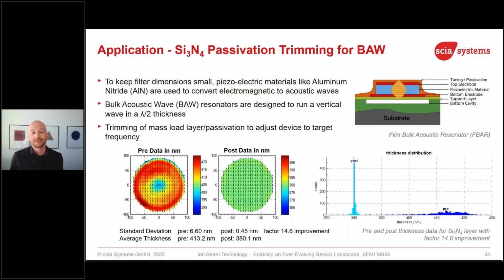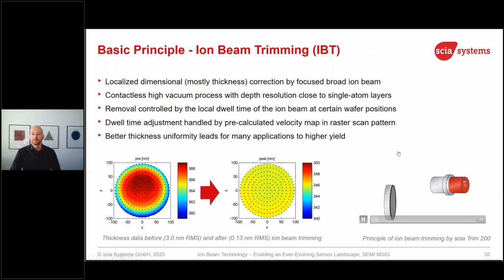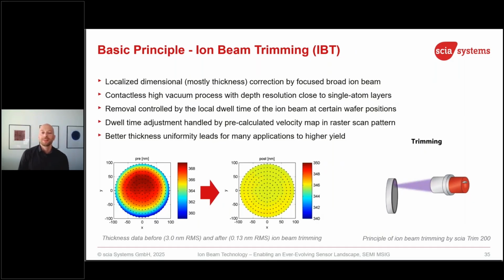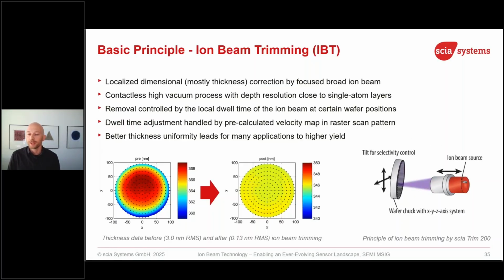Otherwise, your yield is very bad. So we can use a so-called ion beam trimming technology in order to improve this thickness non-uniformity for such BAW devices. How is it done? Actually, each wafer gets pre-measured, and based on those measurement data of the thickness uniformity from each wafer, our system calculates how to scan with an ion beam. The ion beam has a size of about 1 centimeter, and it is scanned over the wafer in order to make it perfectly uniform, so as good as possible.